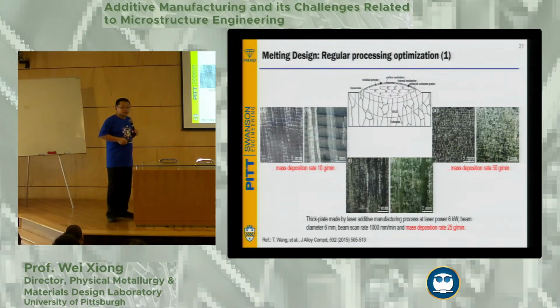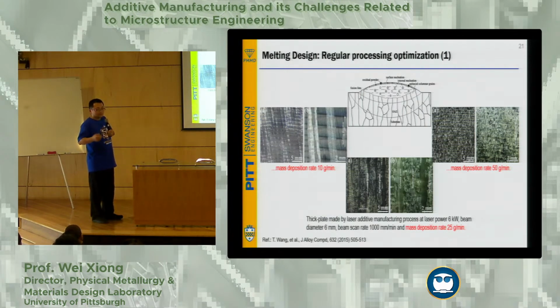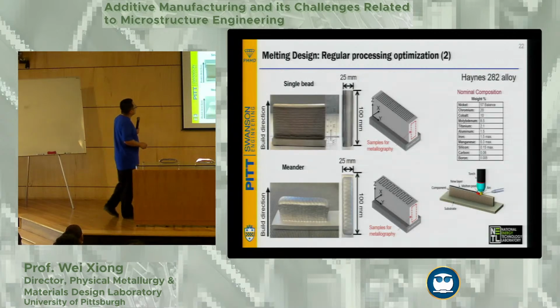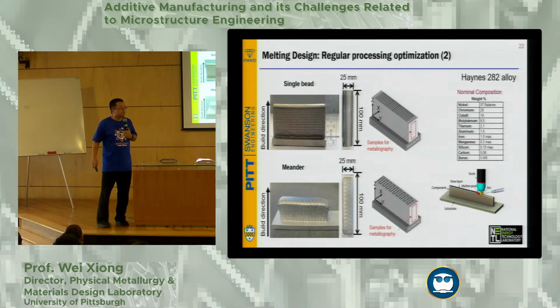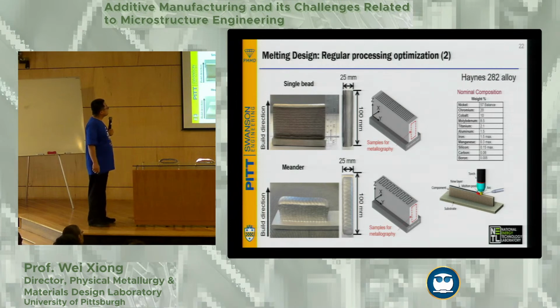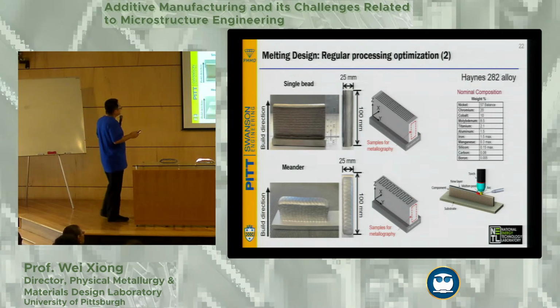All right, and of course, it's very hard to quantitatively do some theoretical design for this. But then with 3D printing, you can do a lot of high throughput. Okay, this high throughput approach, you can actually change the parameter easily with one printing. And you can use multiple processing parameters in order to see the response of the microstructure. So that's actually made it a lot easier to control the parameter relation with the microstructure generation. And this is our work with the Haynes 282. It's a very popular high temperature alloy used in different applications. So this is just showing an example.